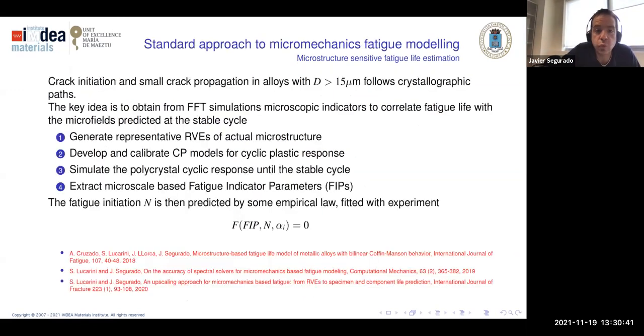This is what we want to try to see here, and we're going to follow a strategy of what we call microstructure sensitive fatigue life prediction. The idea is that we're going to use FFT simulations to correlate fatigue. So we are not breaking the material, we're just estimating the cycles that we need to create a crack. First, we generate RVEs that are representative of the actual microstructure, step one.